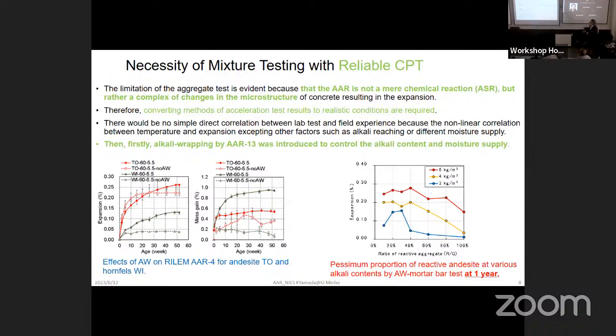Please look at this one. This shows the relationship between the ratio of reactive aggregate in concrete and expansion. This is known as the Pessimum phenomenon. This is the Pessimum proportion. This aggregate shows the maximum expansion at 30% of mixture. And the blue line is the case where total alkali is 3 kilograms. But if this aggregate is examined as 100%, this aggregate is safe if the alkali content is less than 4 kilograms.